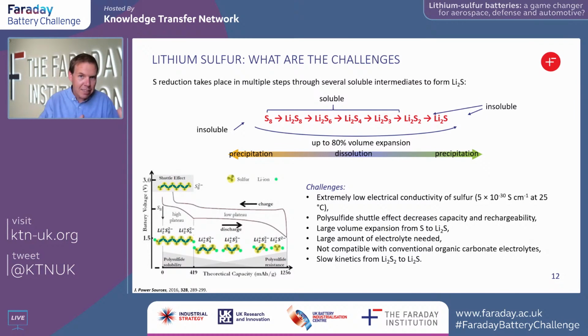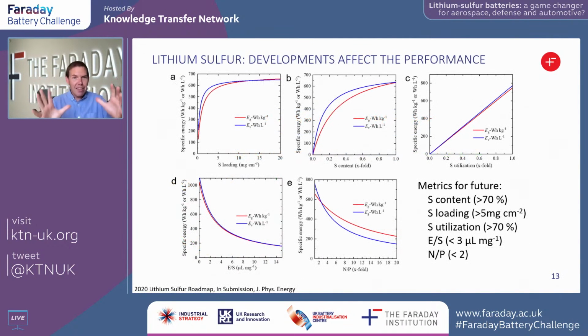And that is key to some of the challenges, but also some of the opportunities within lithium-sulfur. Because the active materials are transitioning between the solid phase and the liquid phase, it gives rise to some of the wide temperature window characteristics of lithium-sulfur batteries. But by contrast, because we have that volume change and that phase change, there are some challenges both from a materials perspective and from an engineering perspective in terms of how we construct the cell. This is the only slide that I've got in the presentation that has a lot of graphs on it, so bear with me while I try and talk through these.